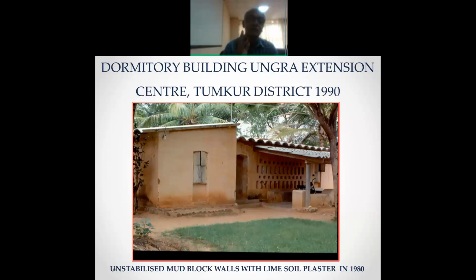This was a fantastic thing because lime slurry is calcium hydroxide. Very soon it will absorb carbon dioxide in the atmosphere, and you have a seamless layer of calcium carbonate, which is an excellent waterproof. So this I did somewhere around 1980 or so. I visited this building 2 years back. It is absolutely intact. We changed the roof to a ferrocement roof. So we have proved that a plain mud block wall will perform if you give a very good plaster, very good waterproof coating. And it has now performed for 44 years.